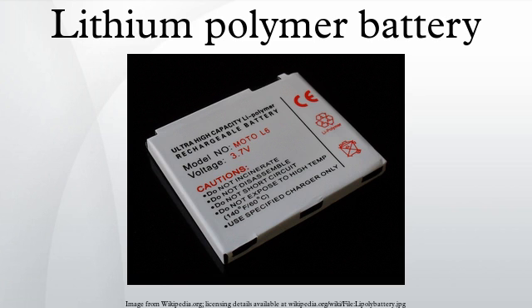Just as with other kinds of lithium-ion cells, the voltage of a LiPo cell depends on its chemistry and varies from about 2.7–3.0 V to about 4.20–4.35 V for cells based on lithium metal oxides, and around 1.8–2.0 V to 3.6–3.8 V for those based on lithium iron phosphate. The exact voltage ratings should be specified in product data sheets, with the understanding that the cells should be protected by an electronic circuit that won't allow them to overcharge nor over-discharge under use. For LiPo battery packs with cells connected in series, a specialized charger may monitor the charge on a per-cell basis so that all cells are brought to the same state of charge.